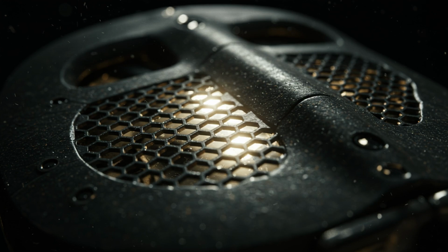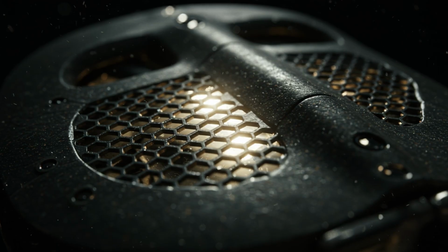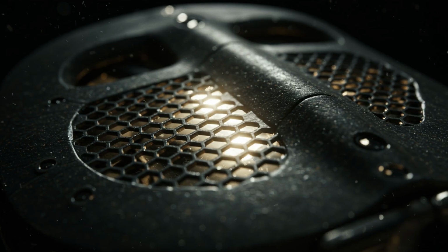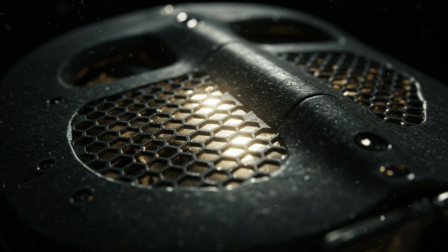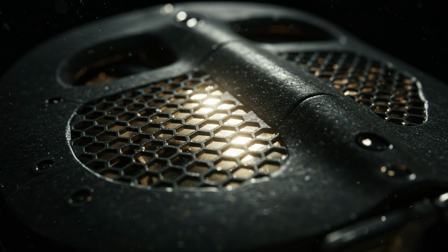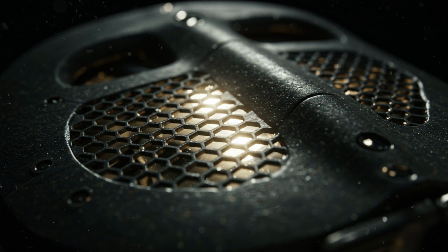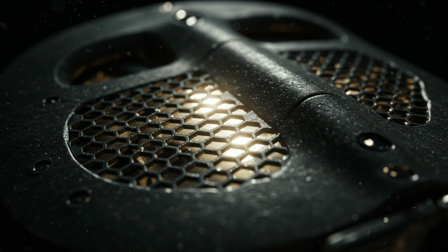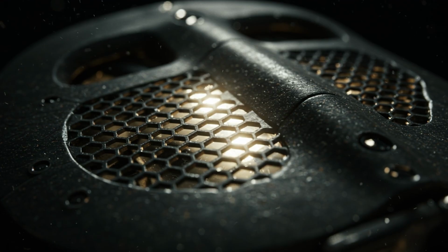The fine metal mask is often called the bottleneck of OLED production because its precision requirements are staggering. Made of a nickel-iron alloy called invar, it is chosen because it barely expands or contracts when temperatures change. This is vital because if the mask shifts by even 2 microns, about 1/50th the thickness of a hair, the red subpixel might bleed into the green one, ruining the color accuracy. To manufacture the mask, lasers or chemical etching create millions of tapered holes. In a 4K display, we are talking about over 24 million subpixels, each requiring a perfectly aligned hole. Gravity itself is an enemy here. A large mask can sag under its own weight, so it is stretched under immense tension and welded to a heavy metal frame. When you look at your smartphone, you are seeing the result of this microscopic stenciling, a process so precise that it pushes the very limits of what mechanical engineering can achieve.